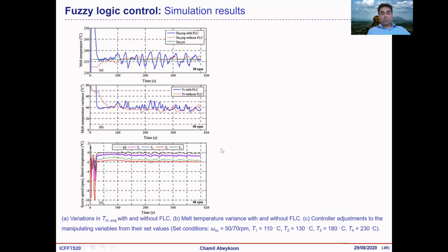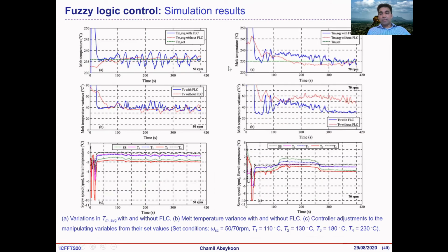This is at 50 RPM. You don't see much difference here, but if you look at the high speeds, as the process speed goes up, the fluctuations are increasing. You can see the temperature variations here. The average temperature with Fuzzylogic is green, and the red dotted line is without Fuzzylogic. You can see the temperature variations are lower with Fuzzylogic than without Fuzzylogic. So this is the actual variation.